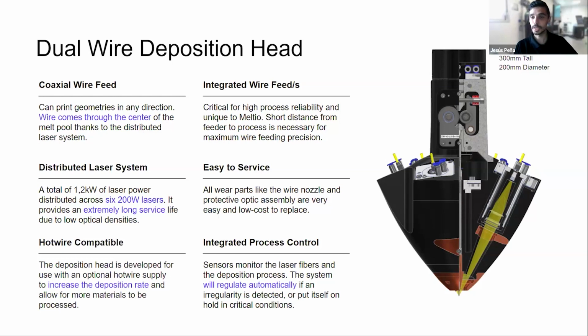The head is completely hot wire compatible. Hot wire is a tool that Michael commented on before. We have the capability of having continuity because we are always touching the wire and the substrate together. So the hot wire is just feeding a lot of current in DC through our deposition head, and then it has to go up to the substrate. We have a short, and the current just wants to flow through the head. Then we have a 1 millimeter or 1.2 millimeter wire, and through there, a lot of current has to pass. So due to the Joule effect, we are preheating the wire, and all our systems are compatible with this option. That is also completely compatible with the process control of the system.